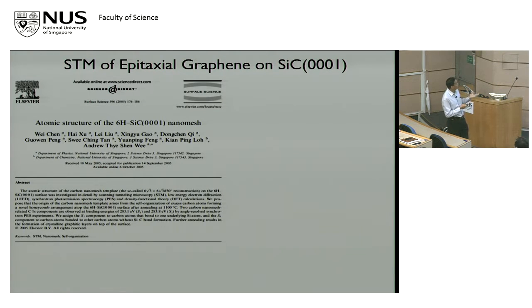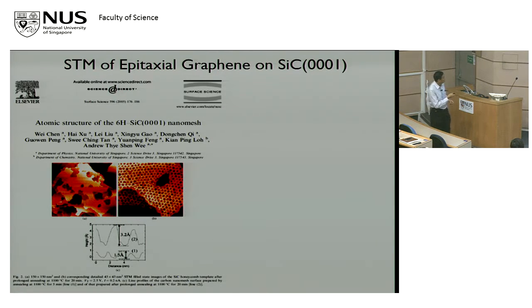So for example, this is part of the work that Chen Wei did in his PhD, where we were studying silicon carbide. We were interested in the atomic structure of a nanomesh reconstruction on the surface that looks something like this. This mesh has an atomic spacing of 2 to 3 nanometers. It actually is the precursor to graphene formation. So you just heat it 100 degrees more, then a graphene layer forms due to more sublimation of silicon. And we actually showed the graphene as well.